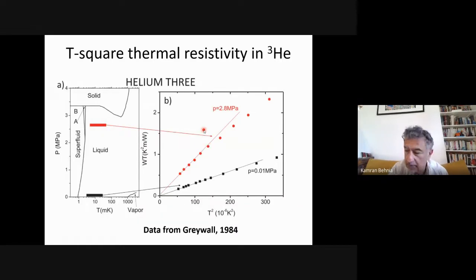So here is the data from Greywall, the paper I just mentioned. This is the phase diagram of helium-3. So this is temperature, this is pressure. You have a superfluid state with two different phases, A and B. You have a normal liquid here. What Greywall did was to measure thermal conductivity in this region. And if I translate his data in the language of metal physicists, you will see that you have a WT term with no residual term, because no impurities here, which has a T squared behavior.